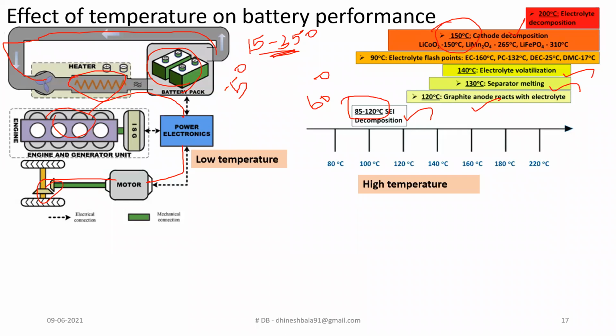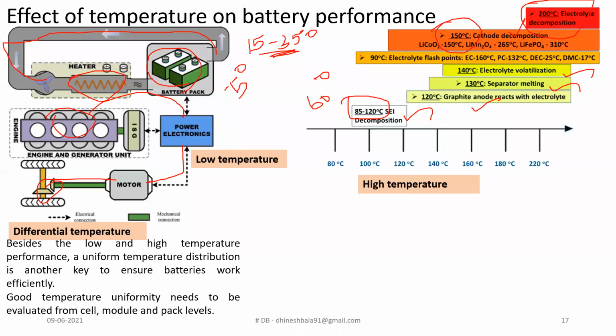So the lithium cobalt oxide would decompose at 150 degrees Celsius. That means the cobalt oxide would not be able to hold the lithium. So lithium would start to react, and that would also affect the battery performance. Above 200 degrees Celsius, the electrolyte decomposition would happen. Because of this issue, the battery fire issue that I addressed in the earlier case might have happened. That is the reason they have recalled all their vehicles and are trying to optimize this issue and safeguard the battery and the market to a greater extent. But in a real-time case, the differential temperature should occur.